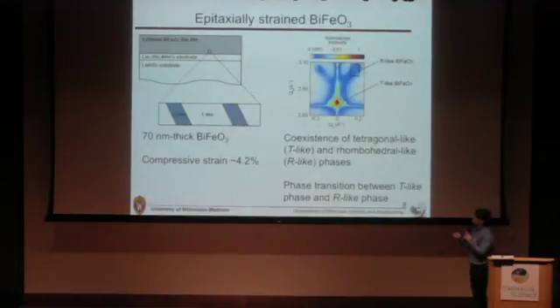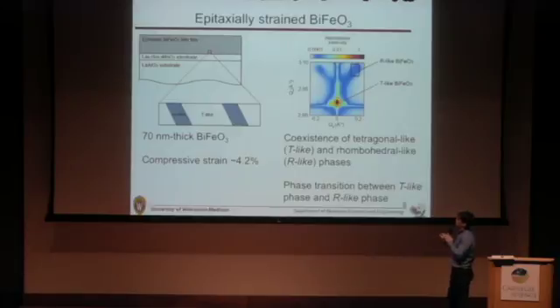And here is the sample we use. We use 70 nanometer thick bismuth ferrite epitaxially deposited on a lanthanum strontium manganite electrode and on lanthanum aluminate substrates. Because this thickness can have the coexistence of the R-like phase and T-like phase at the same time, we can use this system to test our hypothesis. And this is the X-ray reciprocal space map involving the T-like phase reflection and R-like phase reflection. So we use these two reflections to test our hypothesis and measure the intensity and the wave vector of those two phase reflections.